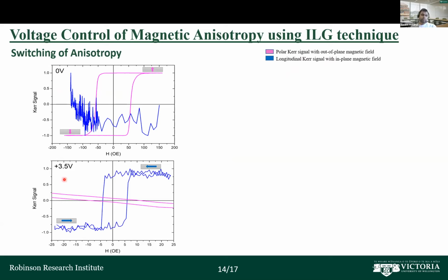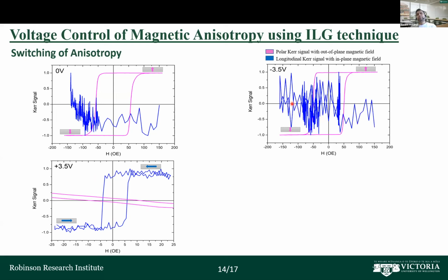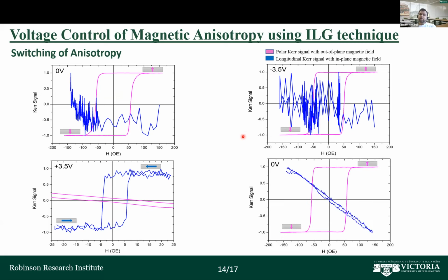But when we apply a voltage of plus 3.5 volt, the anisotropy now changes completely to in plane direction. Again, when we apply a voltage of minus 3.5 volt, the anisotropy changes back to the out of plane direction. And finally, when we leave the stack as it is at 0 volt for a few hours, then it comes back to its pristine state. We were able to change reversibly from the in plane to an out of plane anisotropy almost 10 to 15 times and it is very much reversible.